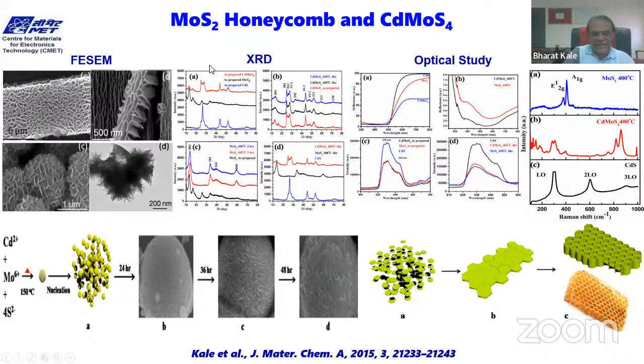Then initially we tried MoS2 and we produced single layer, monolayer and bilayer MoS2. It has a honeycomb-like structure. You see, it's very honeycomb style from the hydrothermal reactor. We explain this in this paper, how this honeycomb structure formation takes place during the reaction. See, hexagonal plates are formed initially, and we first have one-dimensional growth. After saturation, what happens? This one-dimensional growth accelerates the two-dimensional growth, and the vertical growth of plates also gets initiated, and we get this kind of structure.